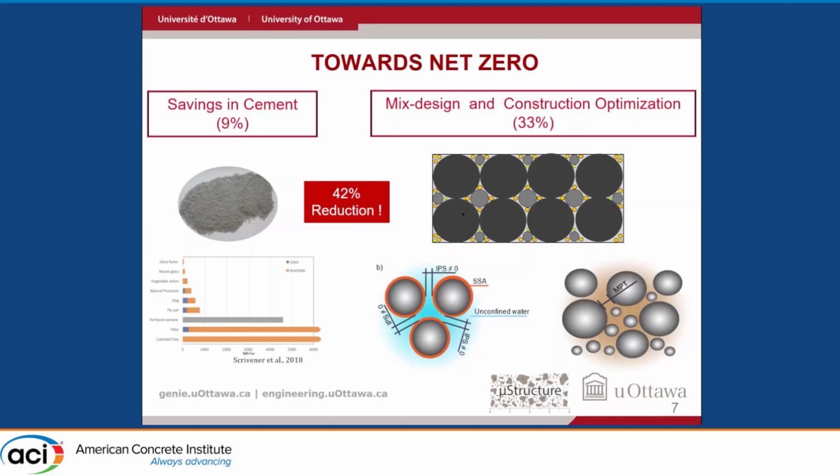We can, instead of just replacing, find a more intelligent way, and I think Konstantin and other colleagues already presented methodologies for doing that. In our work at the University of Ottawa, we are very interested in packing things, but I agree 100% with Konstantin. We are not only thinking about packing without thinking about the distance between those particles, because if I pack too much, I don't have rheological behavior of interest. So just packing is not the end of the story, but rather a combination of packing and detaching the particles so that I get flow.